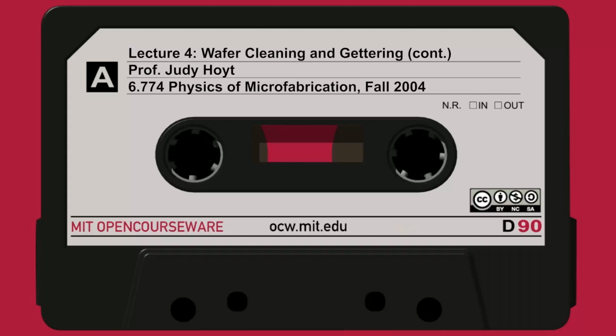So what's rate limiting here is the indiffusion of the silicon interstitials. This sharp drop-off point here, you see at 12 minutes it's dropping off here, 20 and 25, 30 minutes. That sharp drop point corresponds to the depth people believe at which the silicon interstitials must have diffused in a given time. In fact, in the old days, people used this as a marker for how to measure or estimate silicon interstitial diffusion. They couldn't see the interstitials, but they hypothesized they were having this effect on the gold.